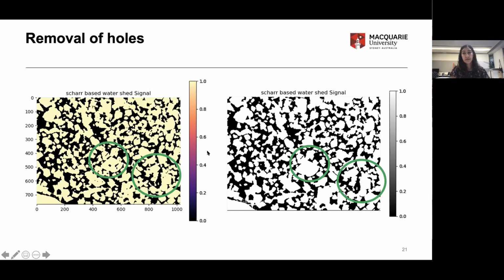This step is also non-essential. If you have a perfect image, you can just skip this step entirely. But it's there for those people who do have problems with their imaging and just want a completely clean image to go forward with. It's at this point that the image is also binarized. By that, I mean that these foreground grains are assigned a grayscale value of 1, and the background is assigned a grayscale value of 0. And that's indicated by this scale bar here.